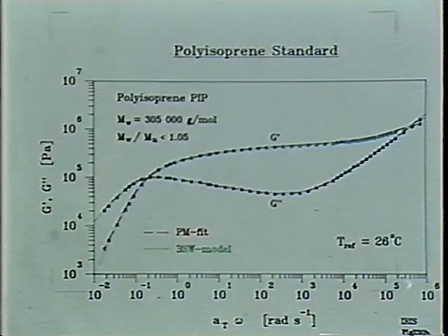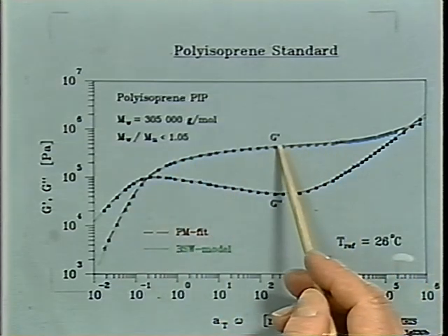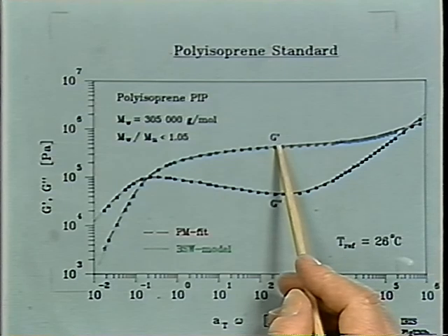We also had a polyisoprene standard, and as you might guess, here, typical feature, linear molecules. Again, we have a fit of the data with the parsimonious model, and with two power laws with the BSW model. And you can see that the parsimonious model is a little better because locally you can fit data with some local adjustment of those Maxwell modes, while in the continuous spectrum, you have only very few parameters to adjust. But the agreement is just going all through here.